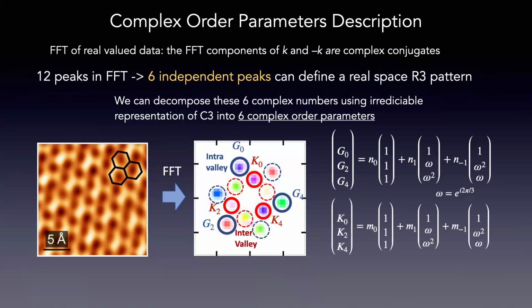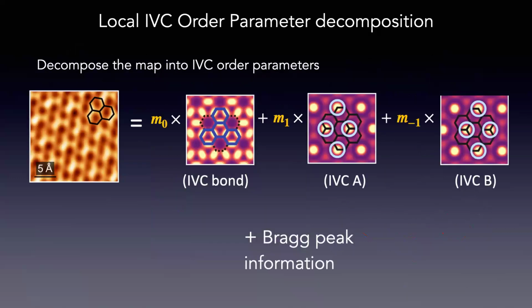And what you do is you represent this on all the possible ways in which you can get density patterns on a graphene lattice. So you go to the irreducible representation. You have 6 complex numbers that describe everything in the data. We are most interested in this intervalley coherence order, which is represented by these 3 complex numbers. For dumb experimentalists like me, you can think of the STM pattern as a combination of 3 different types of IVC. One in which you have density of states on the bonds, which can have its own phase, its own complex order. You can also put the density of states on just one of the 2 sites, A or B sublattice, and you can vary the phase of that. So these are all the possible ways in which you can get a tripling of the unit cell.